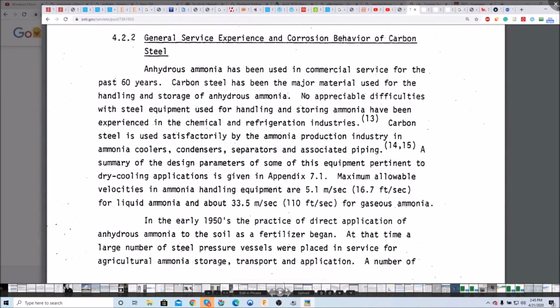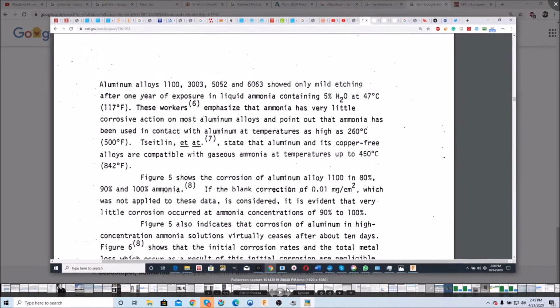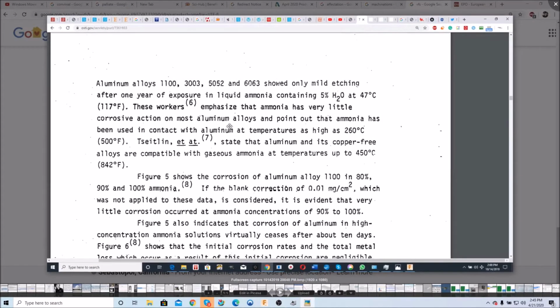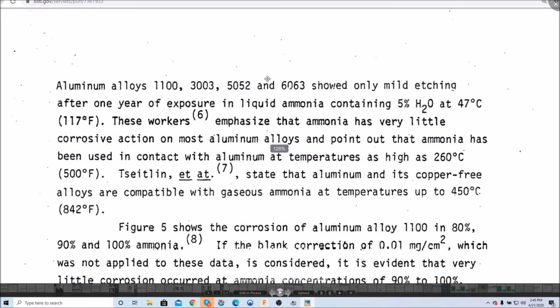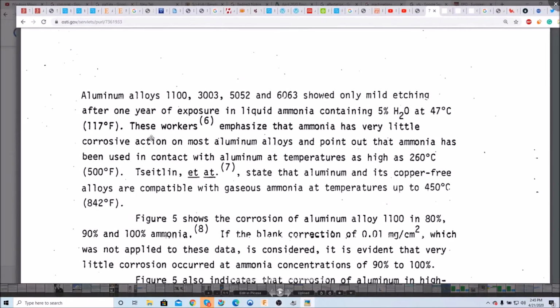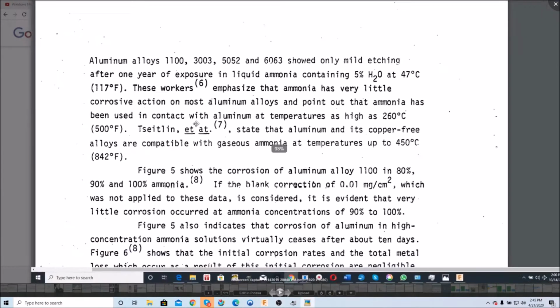Okay, so on the other hand, hydrogen, I don't think, it's used for cooling large turbo generators, but humans are typically not in close proximity to those systems. Aluminum alloys 1100, 3003, 5052, and 6063 showed only mild etching after 1 year of exposure to liquid ammonia. Very little corrosive effect on most aluminum alloys.